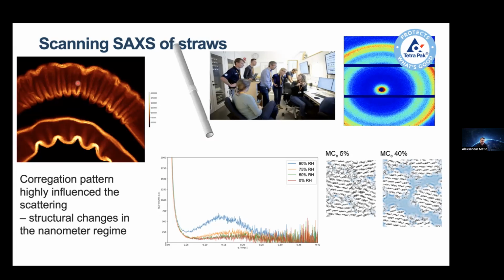And here we zoomed in on the small angle X-ray scattering region, so somewhere down here, and you can see that there are a lot of inhomogeneities resulting from this, which can be a sign that you actually start to influence the surface of the particles, maybe causing cracks, and particles here are fibrils then. In the bottom instead, one can see a much more homogeneous structure. So this was like a first result they directly could get out from this experiment.